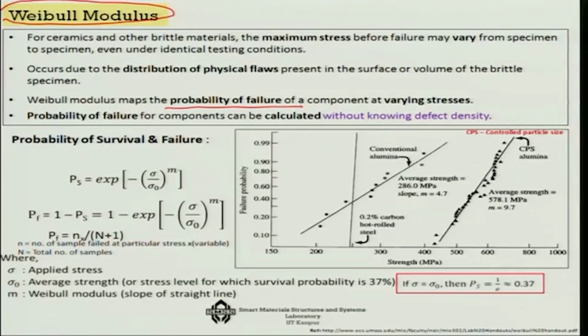Let us say that we are taking some capital N number of samples. With capital N number of samples, I am testing each one of them using, suppose, the 3-point bending test, and I am finding out the stress value at which each one of them fails. Then, at a particular applied stress value, I can find out how many samples have failed at a stress lower than this particular stress value. That will give me the PF. So, Nx is the number of samples that have failed below a particular stress value. Nx over N plus 1 then will give us the PF.